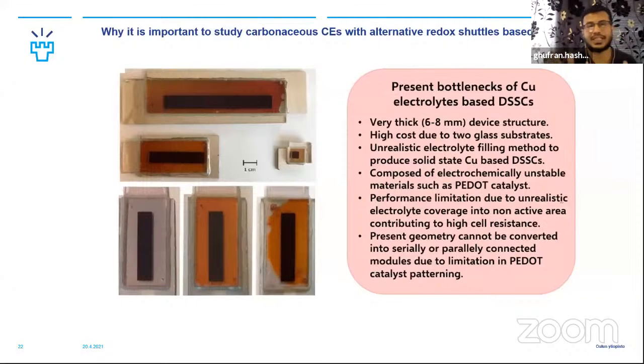Another thing is that this device design is mostly nowadays achieved without any thermoplastic in between, by directly pressing the counter electrode and the photoelectrode substrate, and then you seal it from the edges with a UV glue, and then you introduce the electrolyte in the cell channel. So with this kind of assembly, to the best of my understanding, it is very difficult to produce the traditional serially connected, or even parallel connected, large area solar modules, to achieve higher voltages and more power.